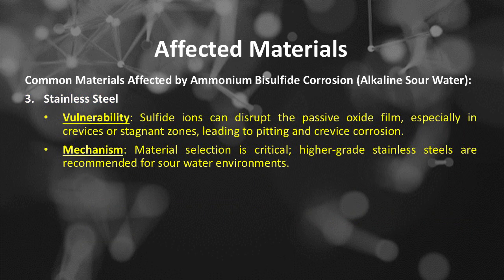Common materials affected by ammonium bisulfide corrosion or alkaline sour water, number 3, is stainless steels. The vulnerability of stainless steels: sulfide ions can disrupt the passive oxide film, especially in crevices or stagnant zones, leading to pitting and crevice corrosion. The mechanism of stainless steels: material selection is critical. Higher-grade stainless steels are recommended for sour water environments.